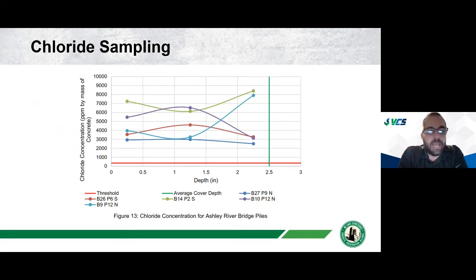And if we look at the chloride profiles for those elements, here's just an example of one. We see extremely high chloride profiles, and the chlorides are pretty straight through the depth of the structure. So you see the threshold's way down here, the average cover depth is here, and we see pretty flat lines. Typically chloride penetration in concrete starts high at the surface and then drops down as the concentration moves into the concrete. You get lower concentrations as you move in.